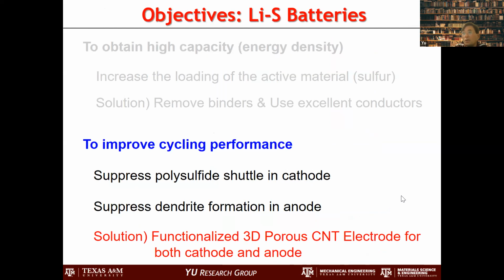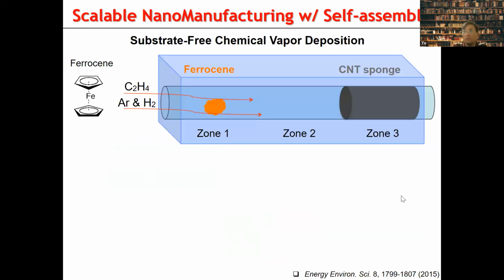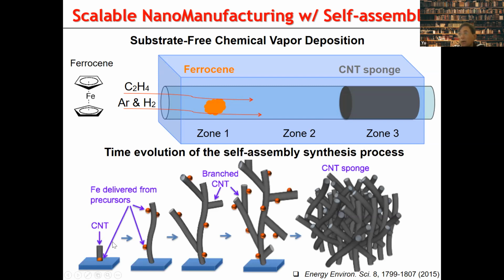So what we have done is we use carbon nanotubes to avoid these two problems. This is our carbon nanotube, and this is how we synthesize it. We use a chemical vapor deposition method, and we flow the carbon source together with ferrocene, which becomes a catalyst. Where the catalyst is deposited, a carbon nanotube grows, and then another carbon nanotube grows, and it becomes like a tree, forming the entangled carbon nanotube.